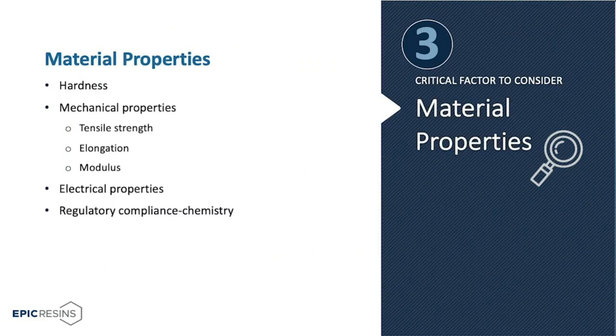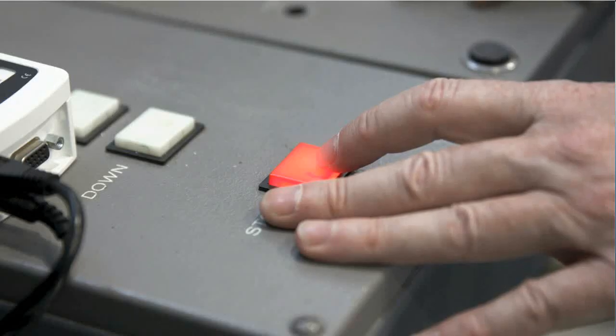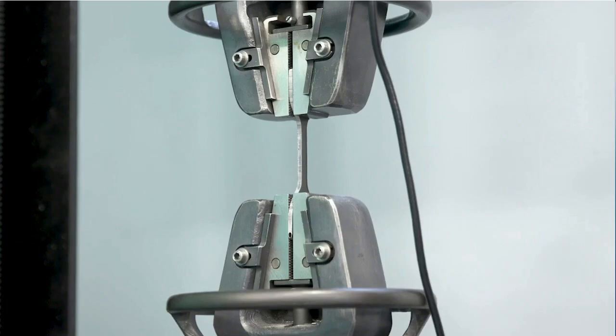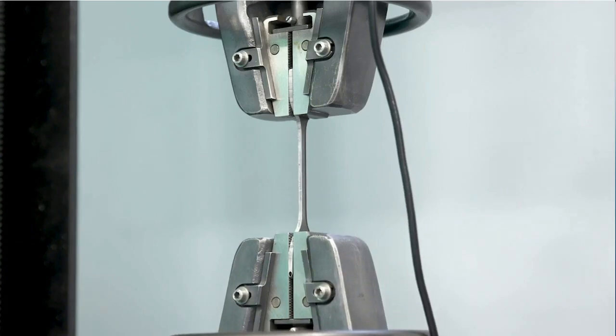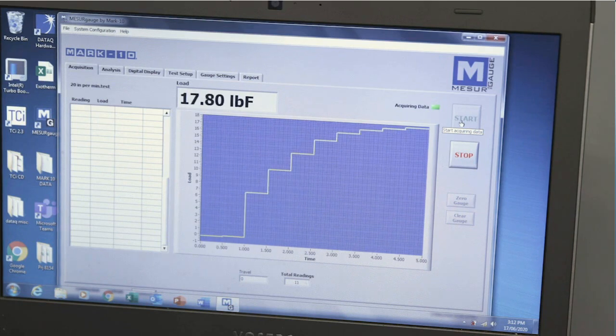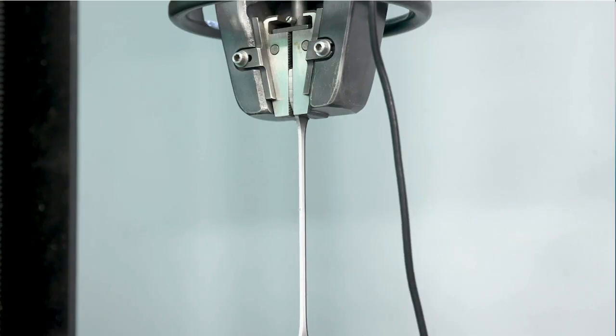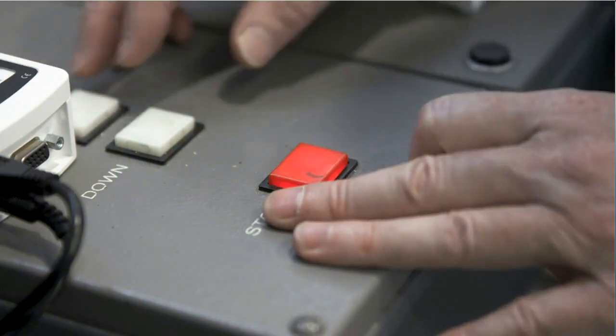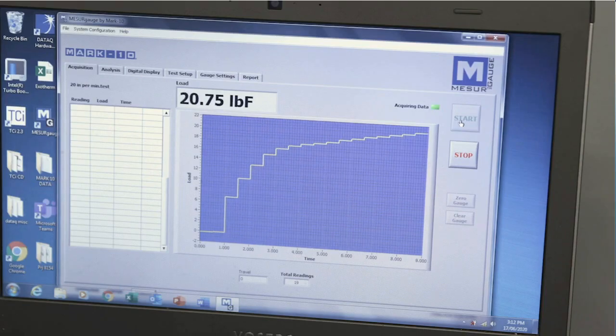countertop. When we talk about mechanical properties, tensile strength, elongation, and modulus of elasticity, all these properties are evaluated using a universal testing instrument. There are two test methods that are used, ASTM D412 for soft pliable materials and ASTM D638 for higher hardness products. Now, as you can see in this video here, this is our universal testing instrument that's testing tensile strength. And ultimately, we take a sample of a certain dimension based on the ASTM, and we pull it at a certain rate. The results that we get from this give us tensile strength, elongation, and modulus of elasticity.